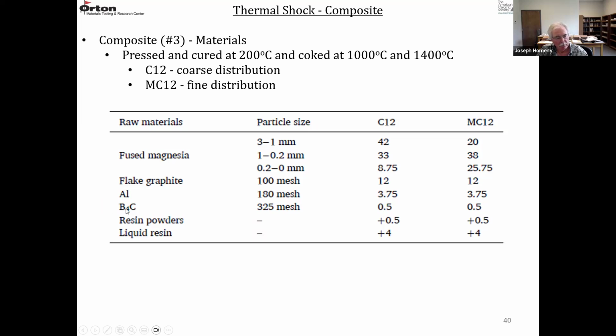The B4C oxidizes and leaves a B2O3 glass, which coats the carbon and is a diffusion barrier. Obviously, if you create a glass, you lower some of the mechanical properties. So in a way, this is a good oxidation barrier, but it does lower the strength. And the resin was a phenolic resin, a powder proportion of 0.5% and a liquid proportion of 4%.